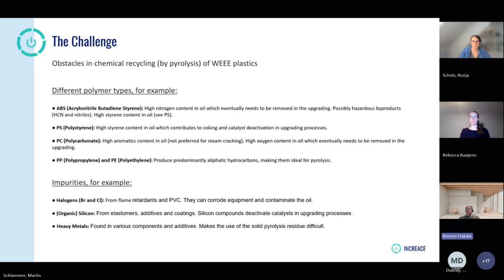Polycarbonate, you get a lot of oxygen, you get a lot of aromatics, also not good for the steam cracker. But from polypropylene and polyethylene, you get only hydrocarbons. Of course, there are impurities, but predominantly you get into the oil product hydrocarbon free of bigger contamination amounts. But impurities that we have are halogens, chlorine and bromine, bromine from the flame retardants, as was said, and usually there's also some PVC or some other chlorine containing impurities. And then silicon, especially organic silicon, is of course the worst.